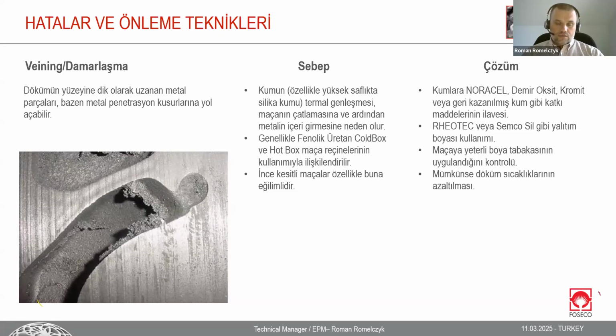To prevent that, you can use special additives to create space for this expansion. You can use special coatings and different recipes, coatings which have a chance to cover the breaks. So the mold or core itself will break, but the coating will still keep the liquid metal away from this breakage, and the metal will not go into it.